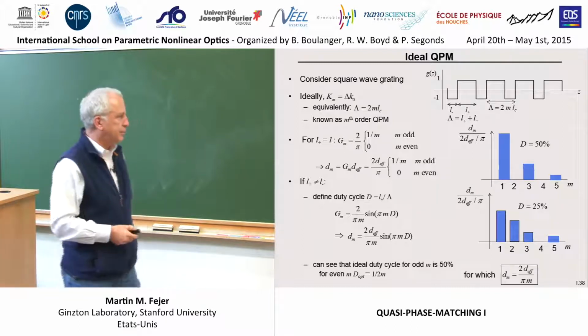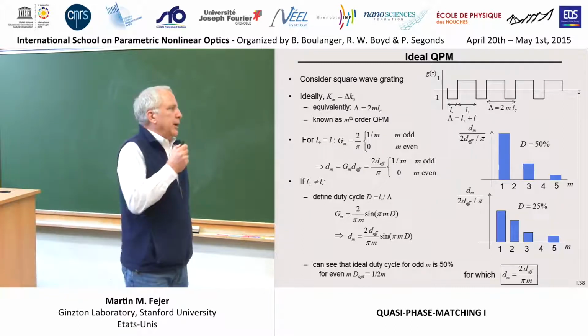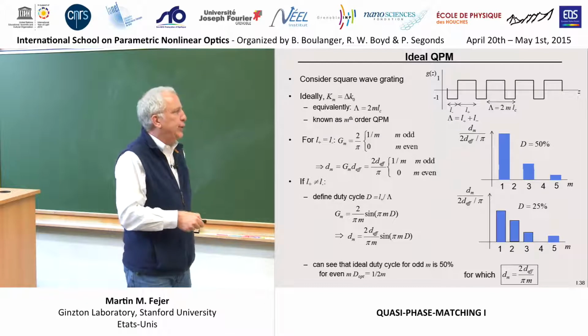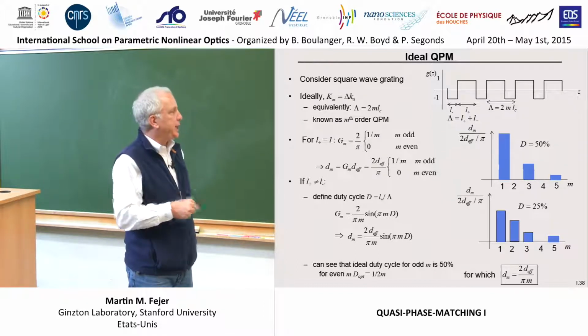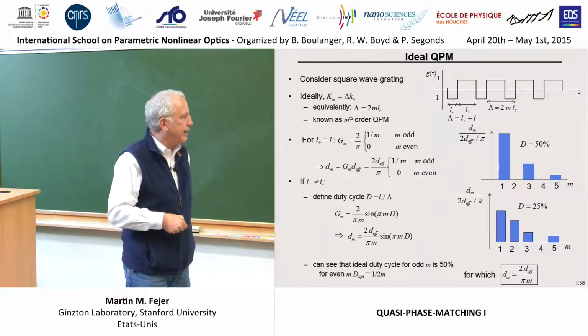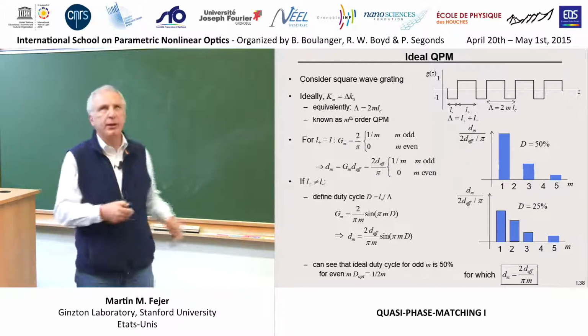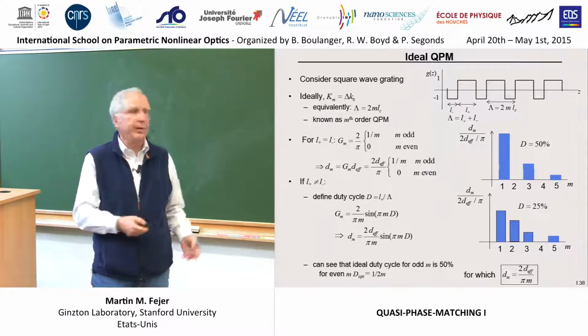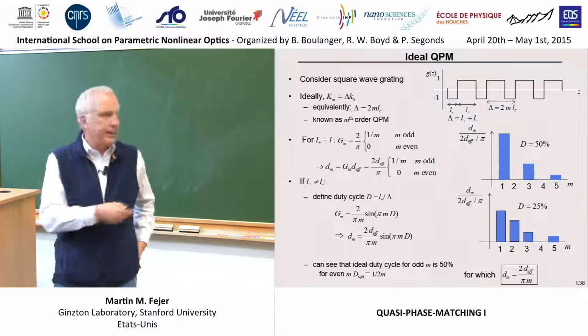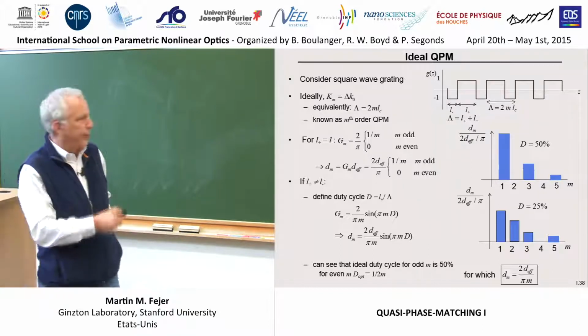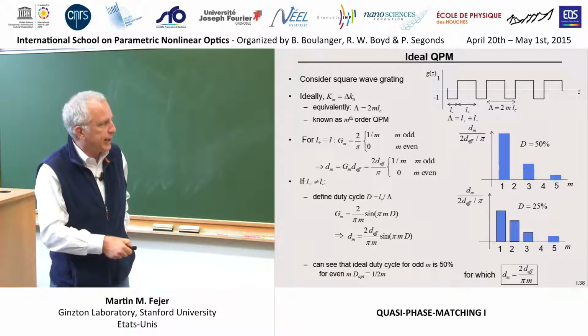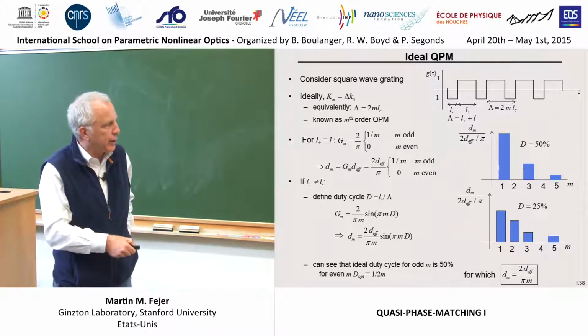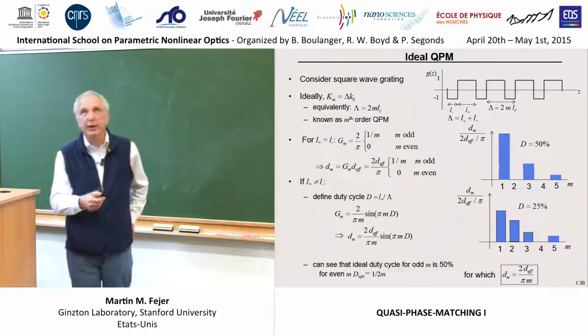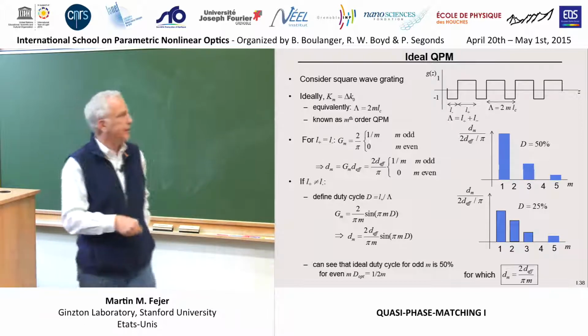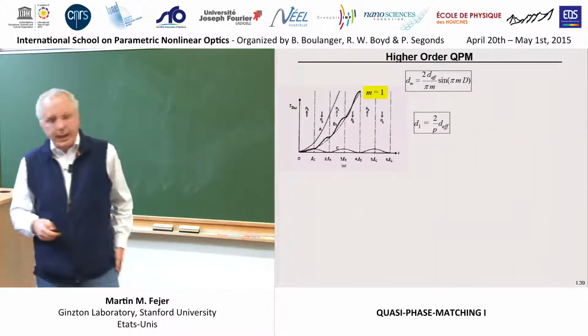And so for odd m, the ideal duty cycle is 50%, equal ups and downs. For even m's, the optimum duty cycle, it turns out, but if you stare at that for a minute, it's 1 over 2m. Let's see, and in both those cases, d sub m then takes that form. It's reduced by 2 over pi m compared to the physical nonlinearity of the crystal. So let's see how that comes about.